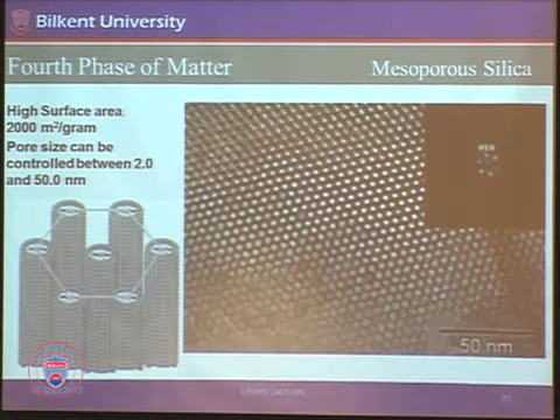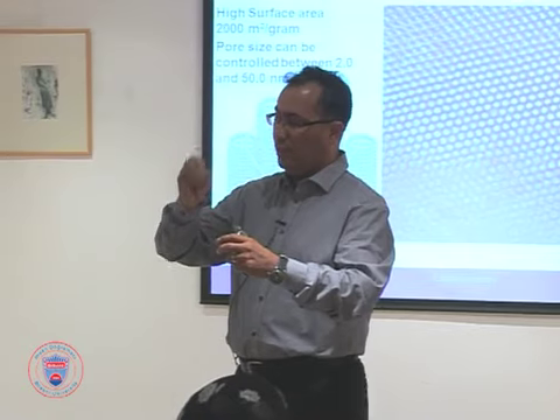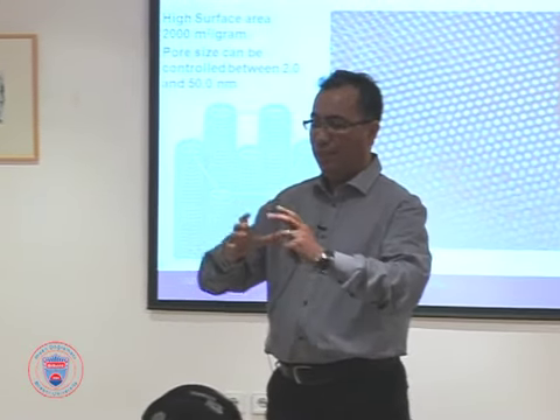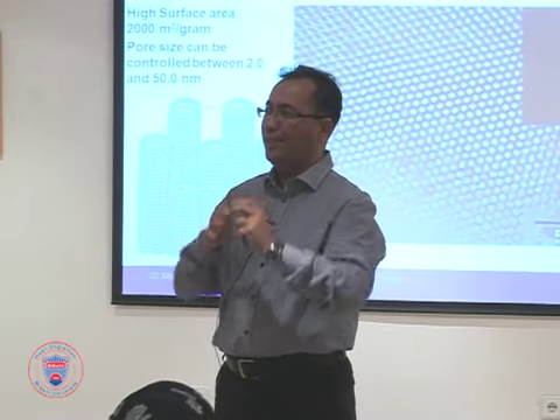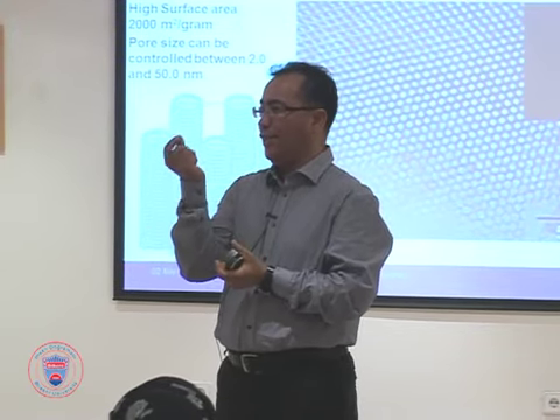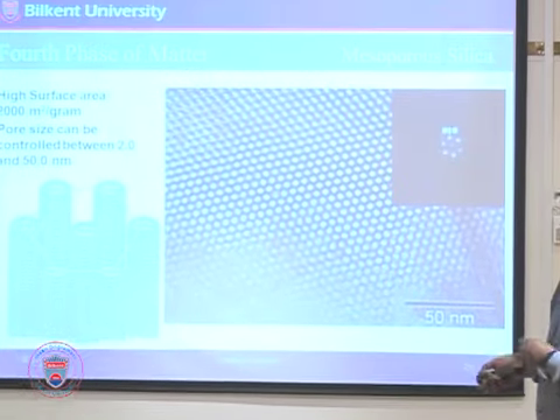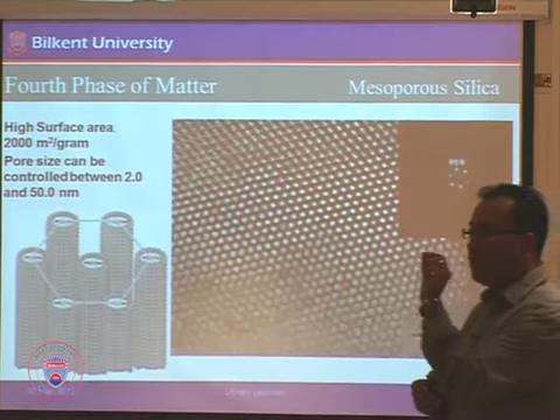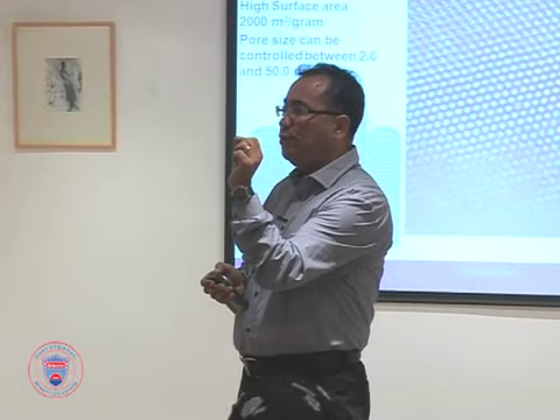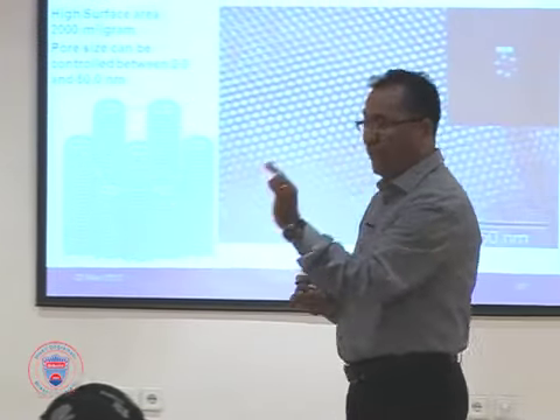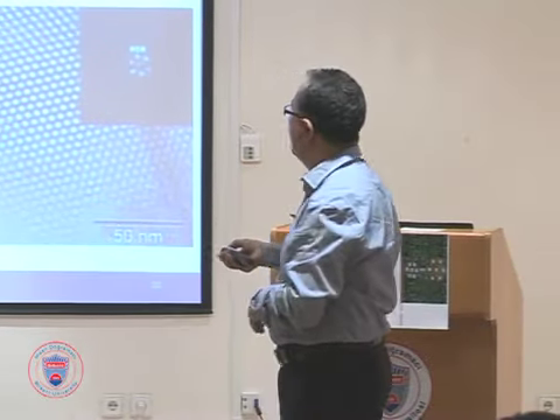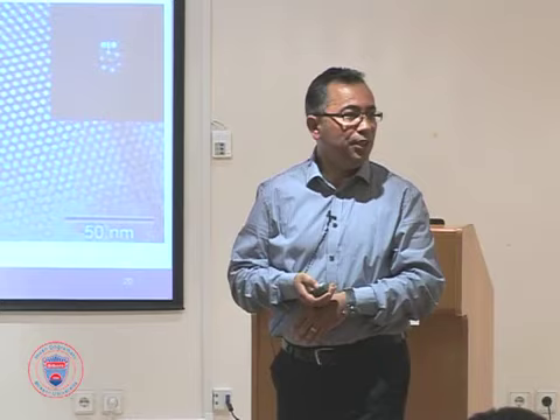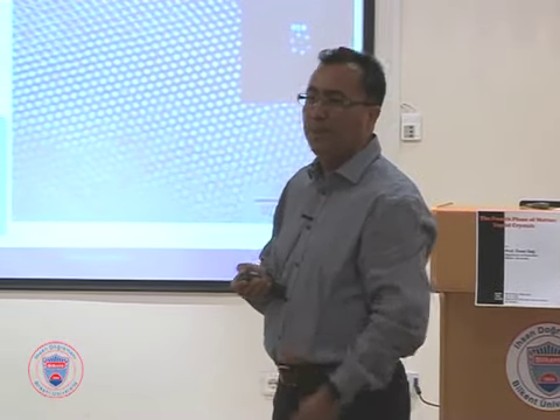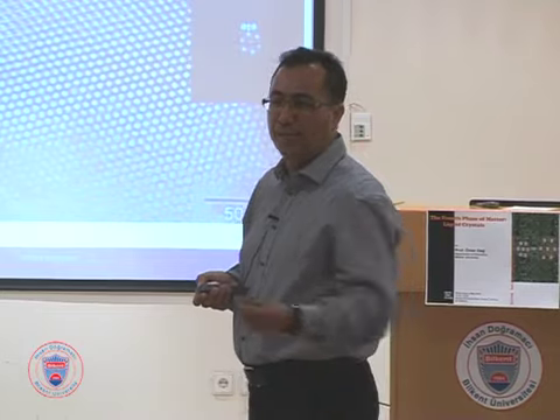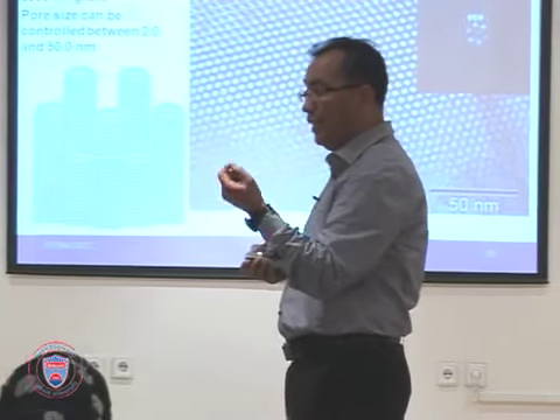And these materials you can picture as, if you have a spherical box filled with test tubes. You all know test tubes, right? And if you look from one angle, you can see holes, right? And these holes are large, we can see. Here, we have a hole, like we have a tube basically. The thickness of this glass part is only 1, 2, 3 nanometer in size. And the opening, the hole in these tubes, can be changed between 2 and 50 nanometer. Okay? Tiny, tiny tubes that you can do chemistry inside, like in our test tubes. You can put chemicals in there and do chemistry there.